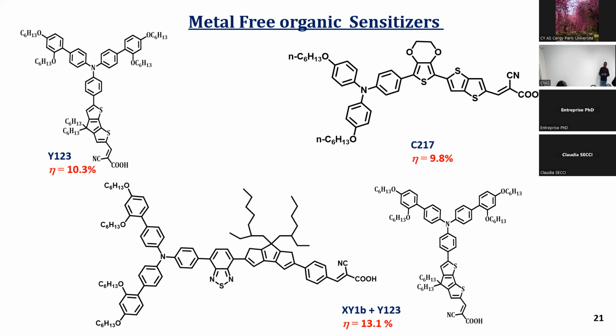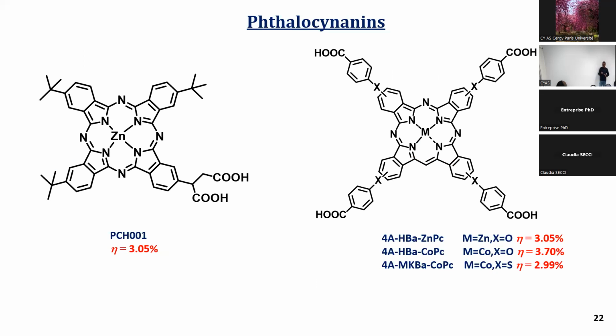And another one, based on extended triphenylamine and benzothiazole with a fused fluorene molecule and phenyl cyanoacrylic acid, with co-sensitizers reached around 13% efficiency. These small molecules also show high efficiency, but the problem is that durability is low. The efficiency reached is high, but there is instability, and the absorption region does not extend to the near IR region. So to overcome this, other molecules were synthesized for DSSC application.